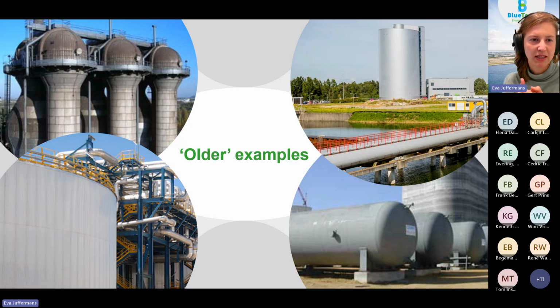And then at the bottom of this slide, you can see 2 different types of high temperature heat storage systems used for concentrated solar power. They are both located in Spain. In the bottom left, you can see a tank where the medium is a molten salt, which can go up to much higher temperatures, about 450, 500 degrees Celsius. And at the bottom right, you can see a steam accumulator, which stores water under very high pressures, making it liquid. And by changing the pressure in the tank, you can accommodate the amount of steam going in and out required for the process for which this was meant. So there are already a lot of examples that are common in industry.